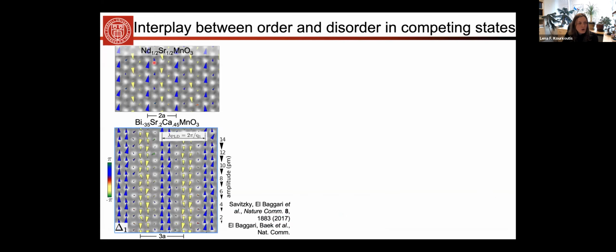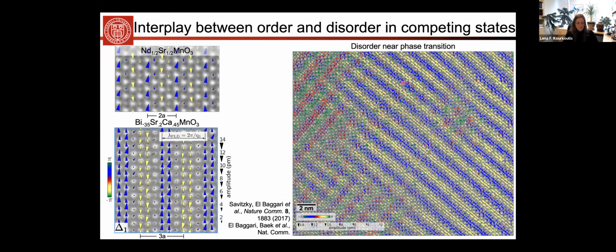Okay, so I showed you the half-ordered system. We can also do this in a 2/3 system where the periodicity changes. The main reason for me to show this very briefly here is to show you that, again, heterogeneity plays a very important role, where phases, the two different colors that you see here, the red-green and the blue-yellow, are competing phases. And you again see areas where when one phase arises, there's disorder. The second one, if you look carefully at the yellow stripes, you'll see that they actually distort.